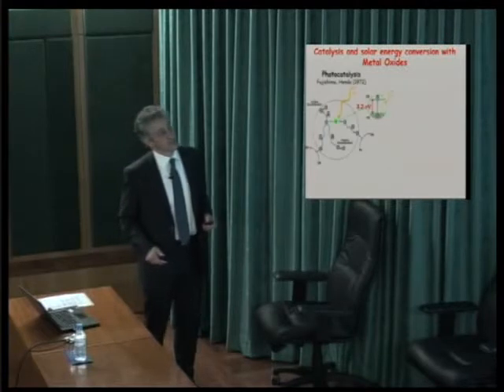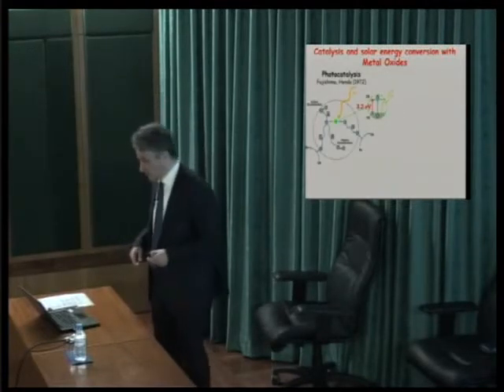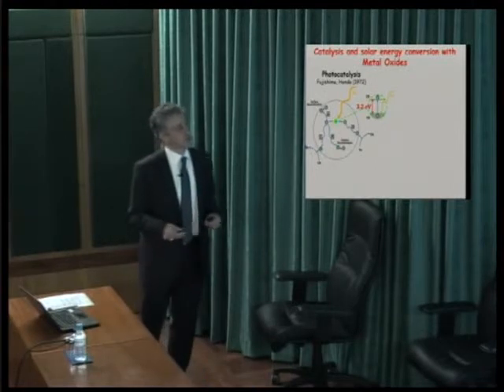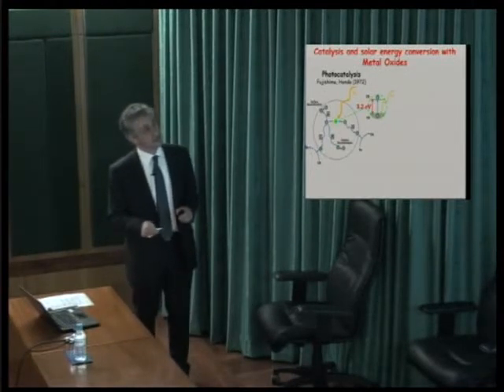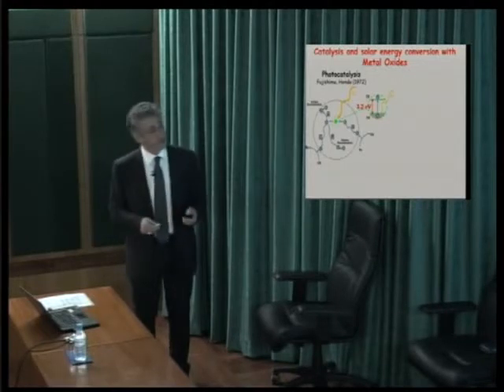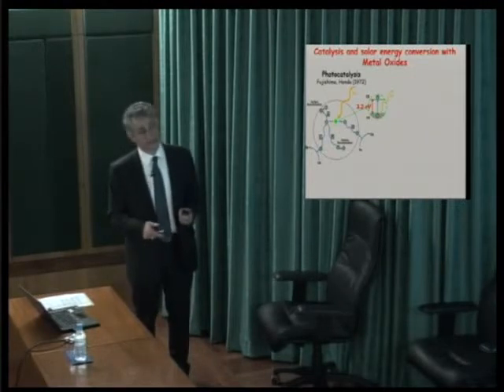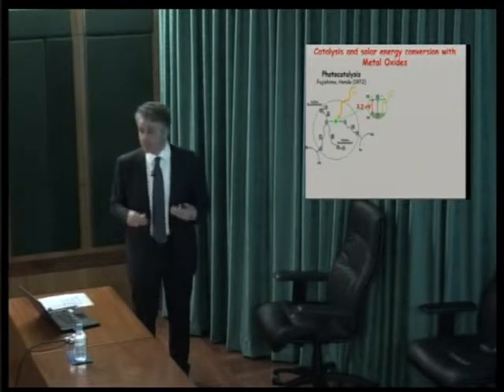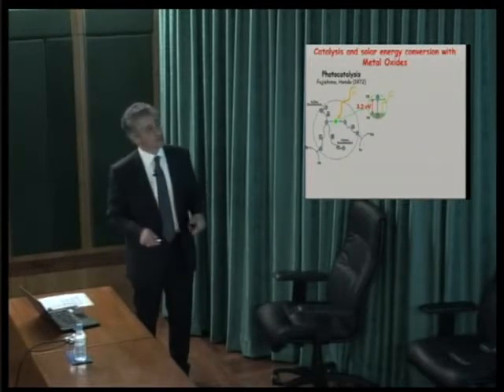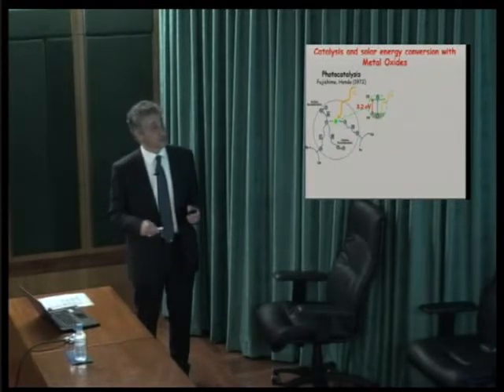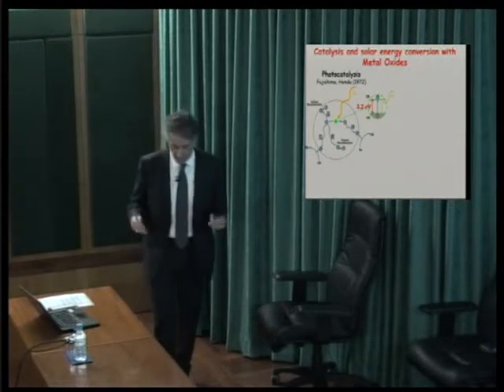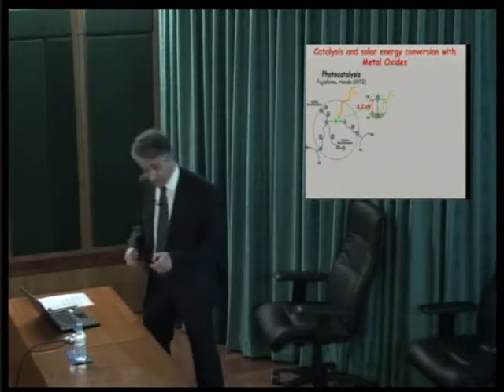Okay, then we looked at solar materials. You know that nowadays there's very hot activity around solar materials, transition metal oxides, and other materials like perovskites. The whole excitement started in the early 70s when, using titanium dioxide, Fujishima and Honda saw that they could split water by irradiating nanoparticles of titanium dioxide. And for photocatalysis, basically you create electrons and holes, they migrate to the surface, and they can take part in oxidation or reduction reactions.